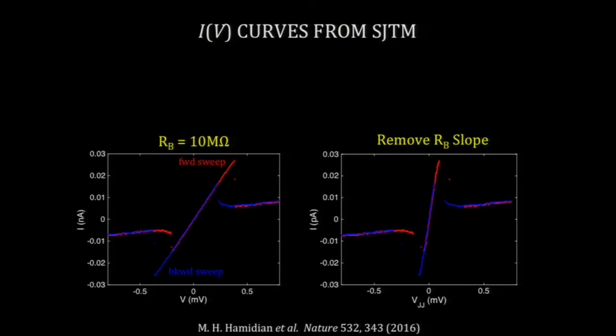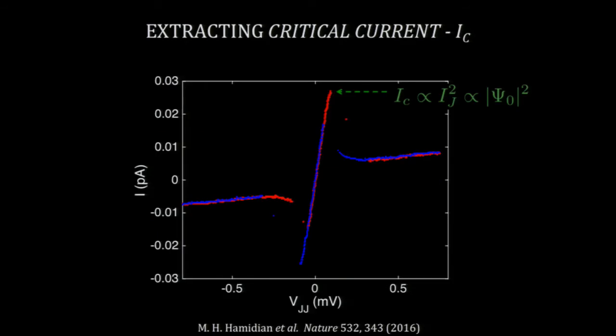So the red is a forward sweep in the current. So you're pushing current through the system in one direction, and blue is pushing it back in the other direction. And here we've removed the slope. There's still a little bit left. We think that depending on how incoherent the junction is, you'll always have a little bit of the slope left over. But effectively, now that you have this set of curves, what you can do is look for the maximum value. And by looking at the maximum value, and I'm calling it I sub c, this is proportional to the critical current squared, which itself is now proportional to the square of the order parameter.